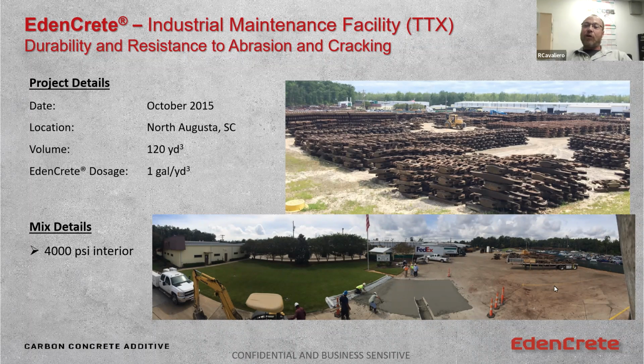So he's seen this concrete being damaged, and he's starting to replace it, and concrete that's older looks better than the newer. So we went out and did a trial. We poured a section without EdenCrete on one day, and we came out and poured a section with EdenCrete the next. This was chosen because of the entryway, and all these trucks pull in. They drive over part of both of these slabs. They stage, and then they back up. They dump their 40,000-pound trailer, and then they drive out over the EdenCrete one, over the reference, and back out the gate. Every day they get 15 to 20 of these deliveries.